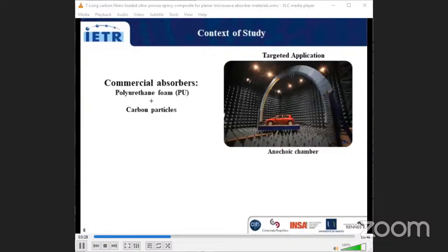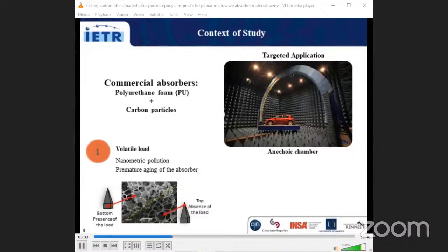On the other hand, these absorbers have some disadvantages. First, the carbon load, which is a volatile escape from the matrix and induces pollution and the premature aging of this absorber. And the second one, the flexibility of this absorber increases machining errors and prevents the realization of complex shapes that can increase its absorption performance.